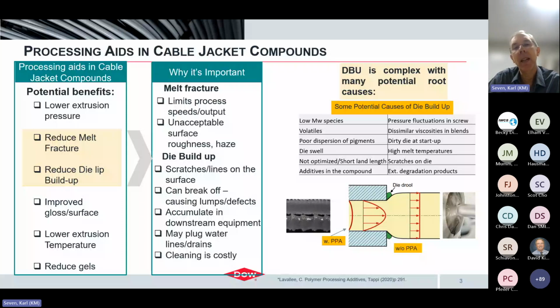And typically what a processing aid will do is it will change the profile of the melt flow through the die. And so this would be the situation of the melt flow without the processing aid, where you have a lot of shear stresses that are occurring at the wall. So it's basically like a drag effect with high shear stresses. With the processing aid, it will even out the profile and reduce those stresses. So that's one mechanism that can help to avoid the die buildup, or at least help to reduce die buildup overall.